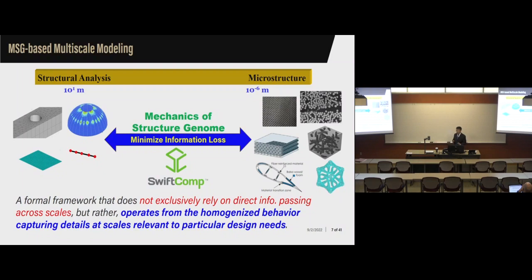So we know what we want at the system level. I want the structure to be modeled in terms of solid elements, plate or shell elements. We also know what it's made of at the material level. Then, thinking from the modeling perspective, you have two models, and you want to avoid the computational cost associated with these details, but you don't want to lose the fidelity. So you also want efficiency at this level, and we can think about how to minimize loss of information between these two model representations. So that's where the mechanics of structure genome comes into play, and that's the only motivation we have. We know the details, we want the global model. And this framework or perspective is different from the traditional multi-scale modeling, because in traditional multi-scale modeling, you find there are single-scale models with data transfer between different scales.